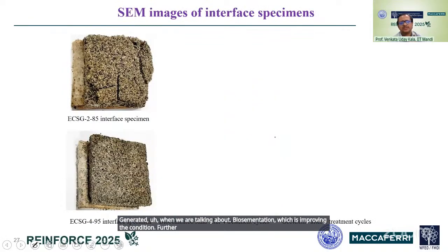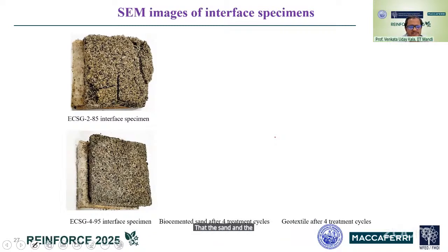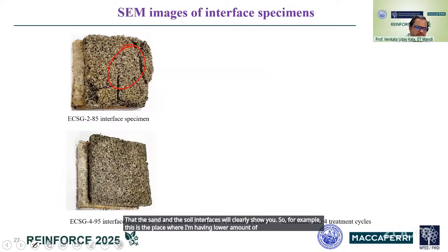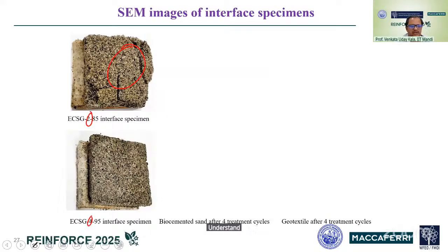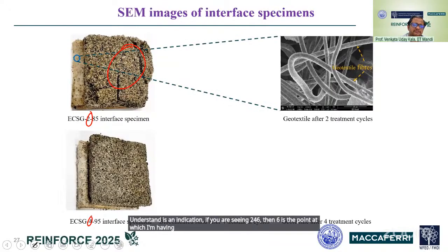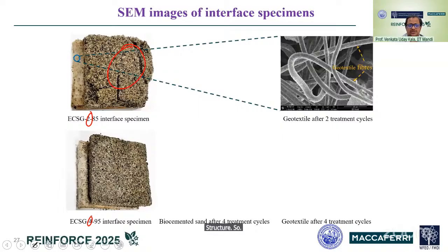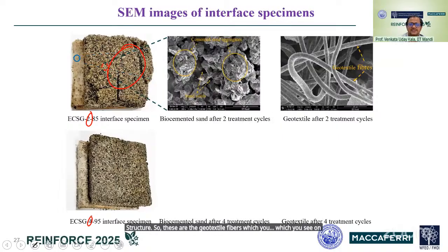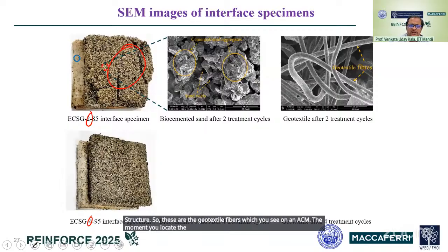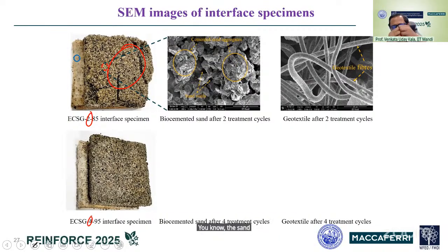Further, when you look into this interface and the type of failures which you might be seeing, the sand and the soil interfaces will clearly show you. So, for example, this is the place where I'm having a lower amount of calcium. So this is an indication. If you are seeing 2, 4, 6, then 6 is the point at which I'm having the highest amount of structure. So these are the geotextile fibers which you see on an SEM. The moment you look into the biocemented sand now, the sand is now coagulated, or probably you will see a mortar as a picture coming into this particular aspect.